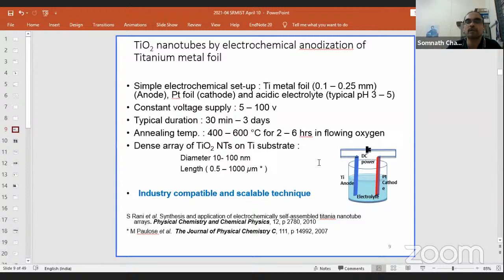Most importantly, we have the titanium anode. Since we are going to make titanium oxide nanotubes, this titanium foil is our starting point. If you do not have titanium foil, for other applications we deposit a titanium thin film on glass or plastic, and then we anodize it. So the titanium works as an anode, platinum as a cathode, the electrolyte, and all you need is a DC power supply. You apply a constant voltage, and then in about 30 minutes you get them. This slide essentially tells you there is a wide variety of processes within anodization, different electrolytes, different things that you can do to get very nice TiO2 nanotubes.